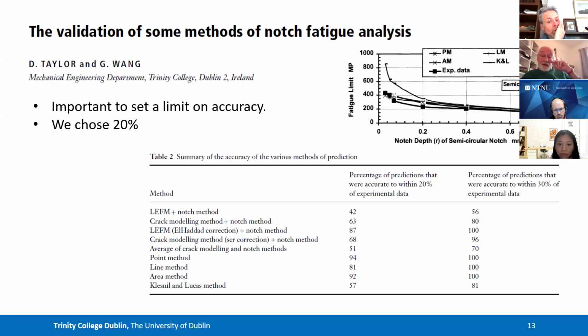So for this paper, we looked in the literature, we found as many results as we could, and we plotted a lot of graphs. There's just one example of one of these graphs here. This is the fatigue limit against the depth of a notch for a semicircular notch, as it happens.